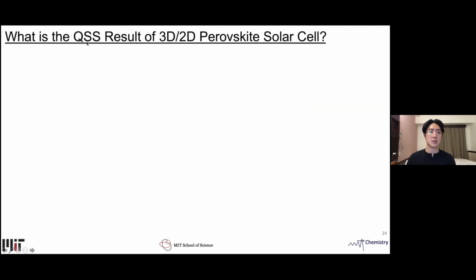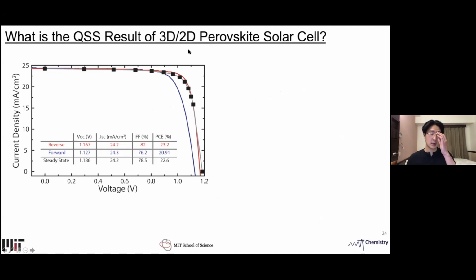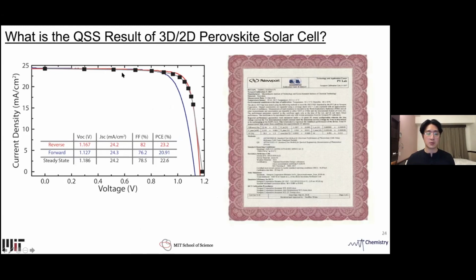So what is the QSS result, or the quasi-steady state measurement, of the 3D/2D perovskite solar cell that was prepared using the SPD strategy? We sent our device to a certified testing center for certification purposes, and we were able to pass the test with a certified steady state efficiency of 22.6%. This was the highest reported value at the time.